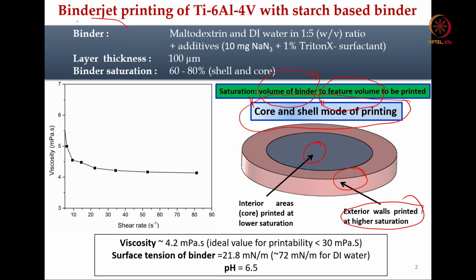So, this particular binder, which was essentially maltodextrin and deionized water, has a viscosity of around 4.2 millipascal second, and ideally for binder jet printing the viscosity should be less than 30 millipascal second. So, that is fine. Surface tension of the binder is 21.8 millinewton per meter, and for deionized water it is 72. So, surface tension is greatly reduced by the use of maltodextrin. pH is 6.5.